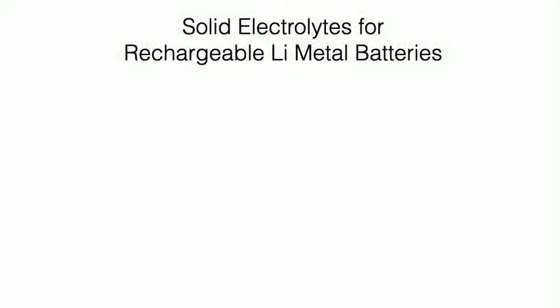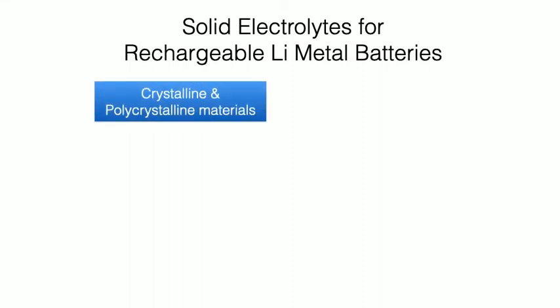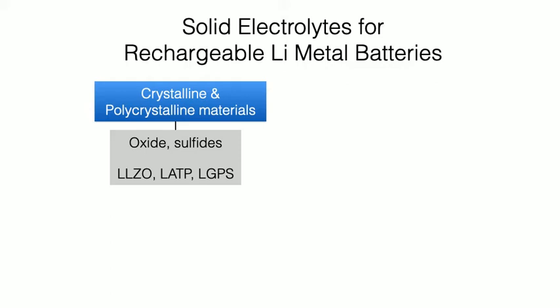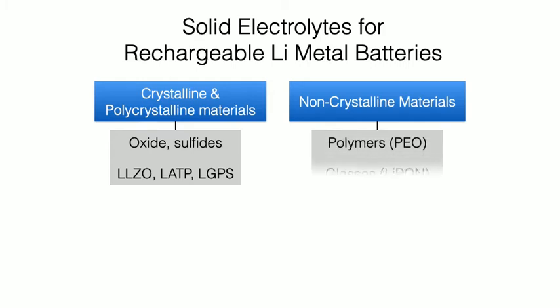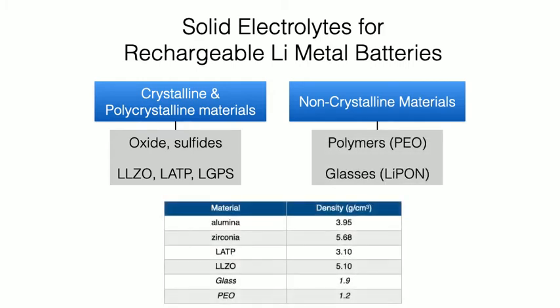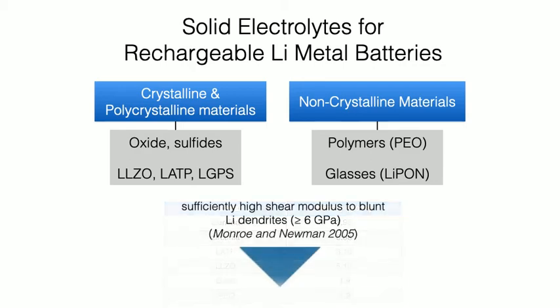Okay, so if we look at the universe of solid electrolytes for rechargeable lithium metal, it looks something like this. On one side, you have crystalline and polycrystalline materials: oxides, sulfides, things like garnet, LLZO, LATP, LGPS. And then there are non-crystalline materials, which would be polymers and glasses. If you look at a chart of density for a variety of materials, polymers are actually low density, which is good because that means they don't weigh much. It's just a passive component in the battery. You don't want it to weigh much. The problem with some of these ceramics like LLZO is they're very dense, which means they're very heavy. So that's an issue.